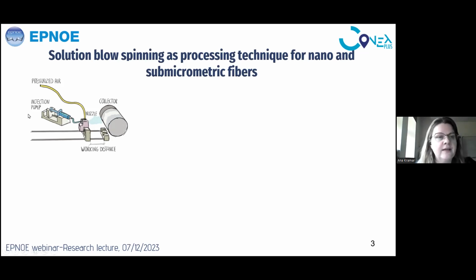Here, I hope you see my pointer, in this scheme you can see that the first step is, of course, to dissolve our polymer. Then by using the injection pump, we deliver the polymer to the nozzle. At the exit of the nozzle, we have connected pressurized air, which is the driving force for nanofibers delivery to the collector, which is positioned at a certain distance from the nozzle. At the same time, this pressurized air helps evaporate the solvent. So it's very similar to electrospinning, a well-established technique for nanofibers, but instead of an electric field, the driving force for nanofibers formation is pressurized air.